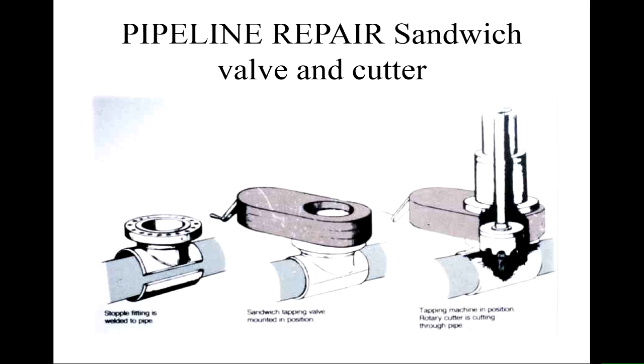So now you've got to put a hole in. If we're going to actually divert flow into this T, we're going to have to let the gas get from the main pipeline into the side pipeline, which means we need to cut a hole in it. And you can do that while the gas is flowing. And you do that by putting on the split T, putting on a valve, a tapping valve, and then putting on a hole saw above that valve. It's all gas tight. So once this is all connected, then you can open the valve and then run the saw, but the gas can only get into the inside of that body unit.